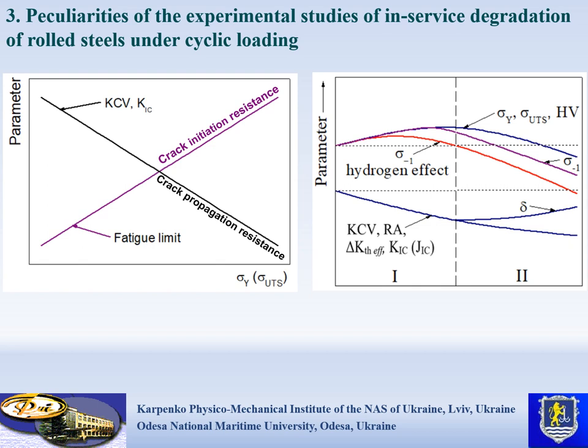Peculiarities of experimental studies of in-service degradation of rolled steels under cyclic loading. First of all, it should be drawn attention to the generally opposite effect of strength on fatigue strength of smooth specimens and brittle fracture resistance like impact strength and fracture toughness. Fatigue limit detects rather crack initiation resistance, while impact strength and fracture toughness detect crack growth resistance.